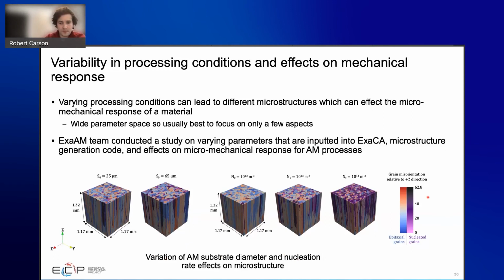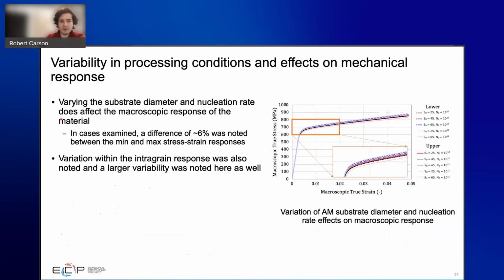But one of the things that we found was even though we varied a lot of these, and there were some large differences in the average grain diameter, you really only saw minor differences in the stress strain response in this 5% strain that we're looking at. We only saw a 6% max difference between the min and max response when we were just looking at the macroscopic response. Although we did see a much larger set of differences when we started looking at the intragrain response, which was expected.